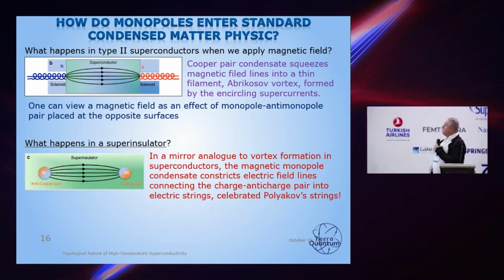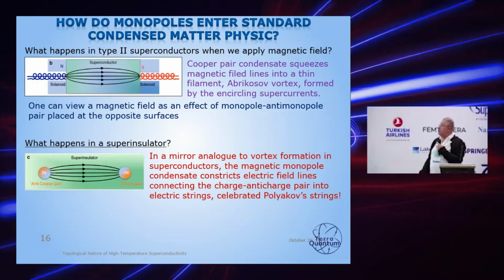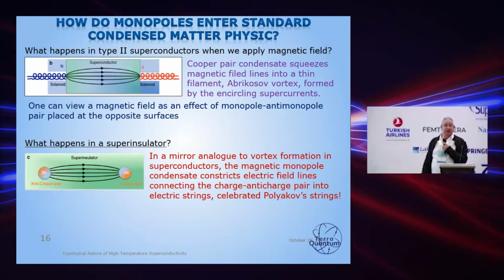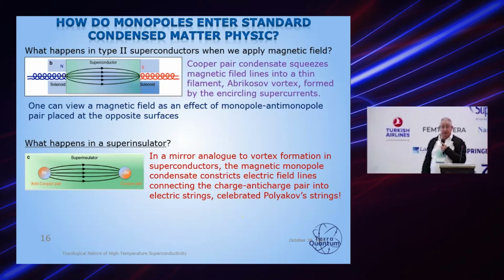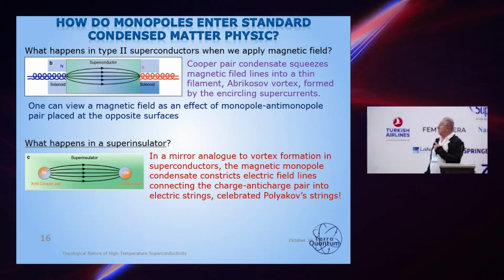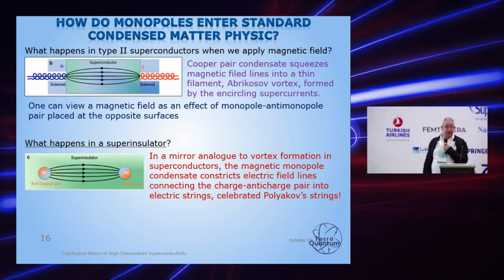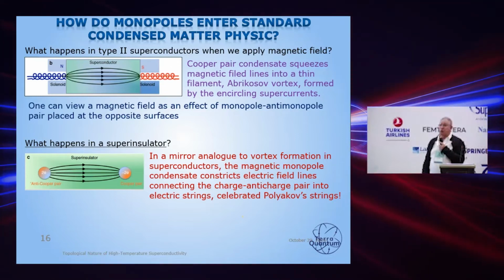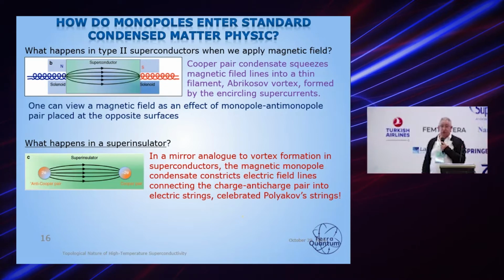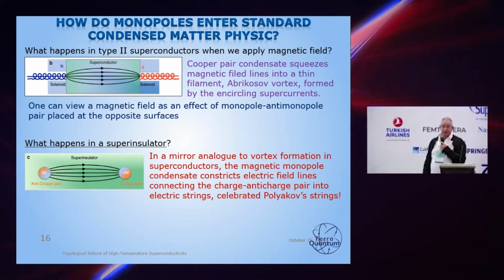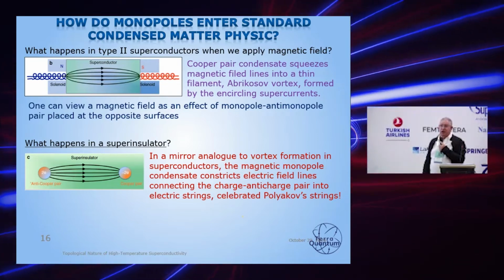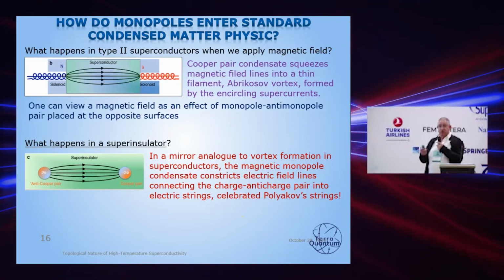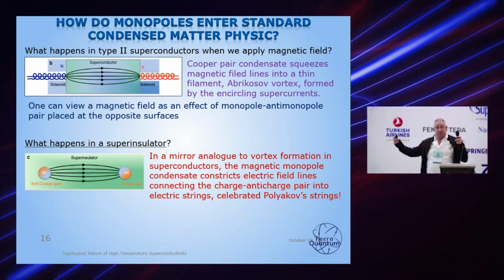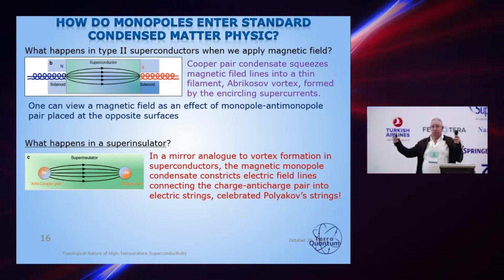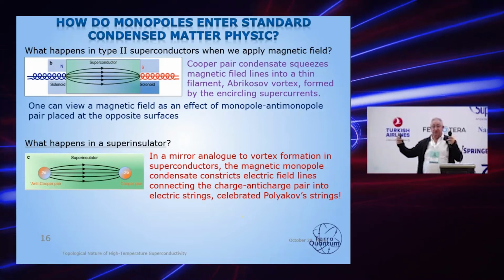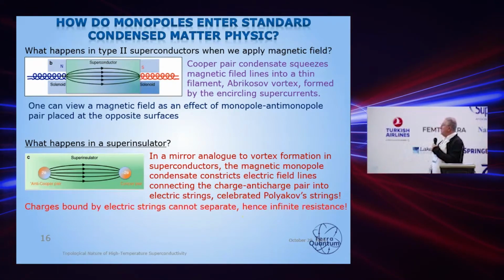And exactly the same happens in a superinsulator, but just the opposite. If we have two charges, then the current of the monopole condensate squeezes electric lines into electric strings. And actually the strings are very well known to people doing field theory, those are Polyakov strings. And those are exactly Polyakov strings, which prevent charges from moving, because if you try to take them apart, this string tension doesn't allow them to move. That's why we have infinite resistance.